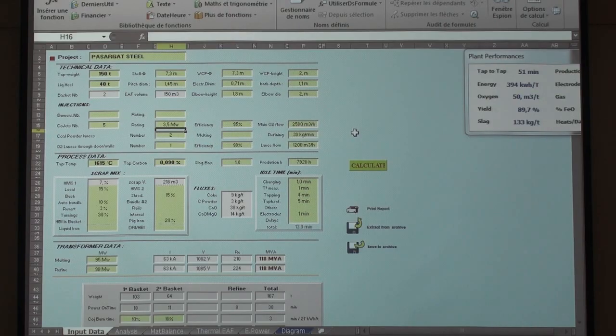But the other technologies, they put in the wall burners, carbon injections in the wall, and the carbon lances are assembled in the slag level. Yeah, they claim in the slide, but it's not really, it's above the slag. With foamy slag, at the first melting time the slag level is low, and then increases. They can put the lances in the center of the slag and charge the carbon. It is one of the solutions. It's good, it's working well.